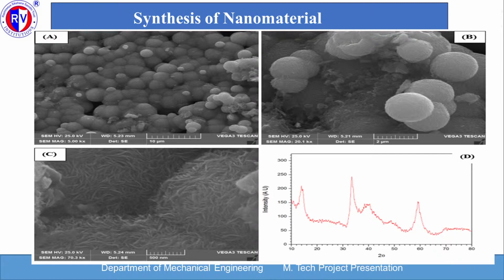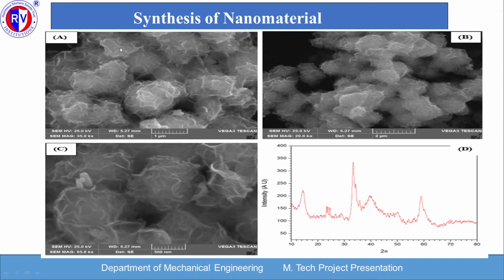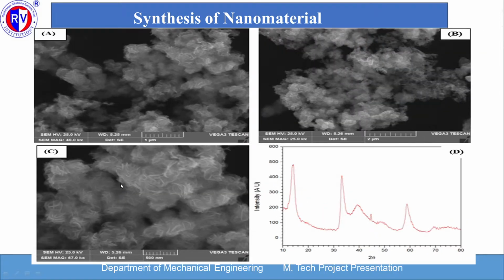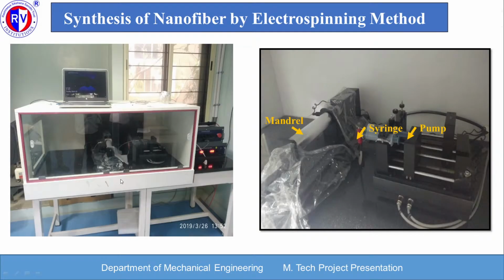These are the results from the first set of experiments. Sphere-like structures are present, and at further magnification we can see that in those spheres fiber-like structures are present. The MoS2 presence is confirmed by the hexagonal crystalline structure. This is the second set of experiments. In this set, spongy cotton-like structures are obtained, and in the third set, the same clusters of spongy cotton occur.